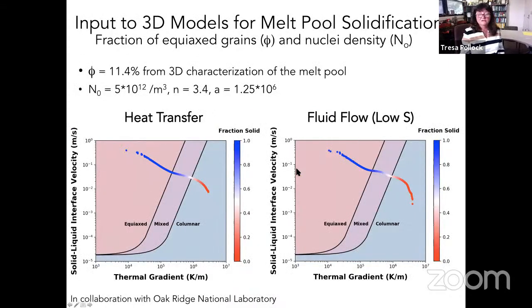And so we're able to use that information now to build models to predict structure. And so here I show two maps of velocity and thermal gradient for two different modeling conditions, one which only has heat transfer, one which includes fluid flow. And now that we have all the information, we can track the fraction solid from 0 to 1 through these transitions in structure as we go from fully liquid at fraction solid 0 to the grain nucleation events at the end of the process. And so it is still early days for having models that accurately predict all of these things, but one has to work your way through the problem in terms of gathering all the critical data.